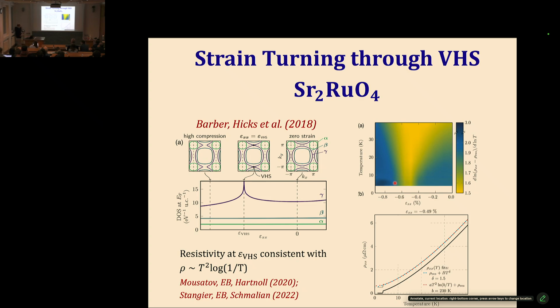Typically, if you have an energy-dependent density of states, which you always do, you won't see a pure t squared. As long as the density of states at zero energy is constant, you'll see asymptotically t squared at very low energy, unless you have some singular density of states like you do here, but nothing more exotic than that. This can be perfectly described using Boltzmann transport.